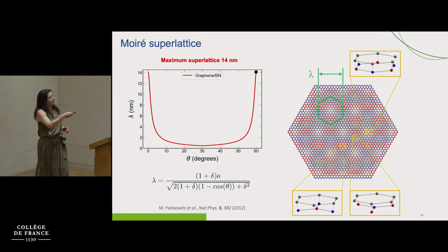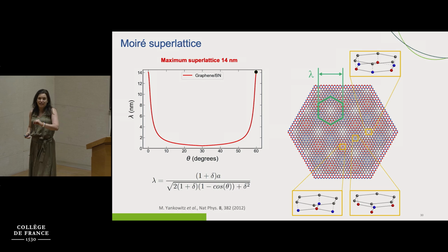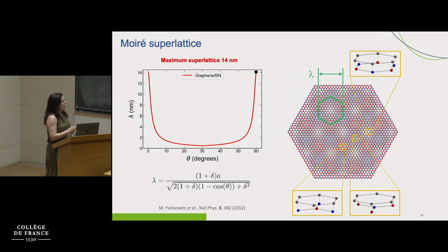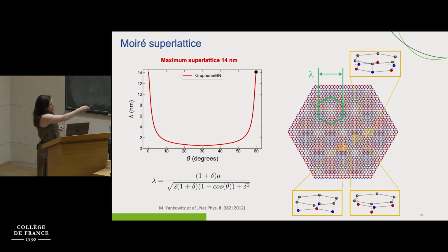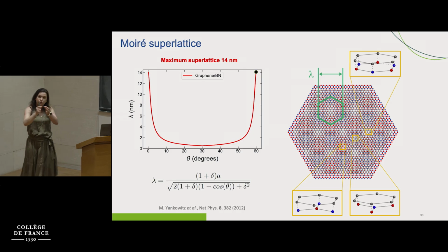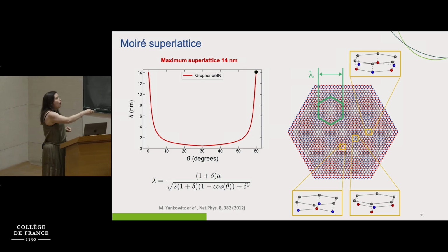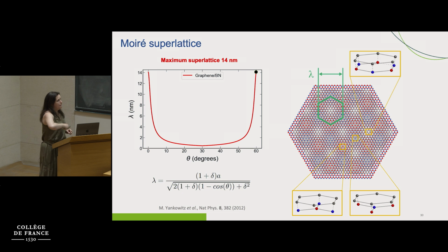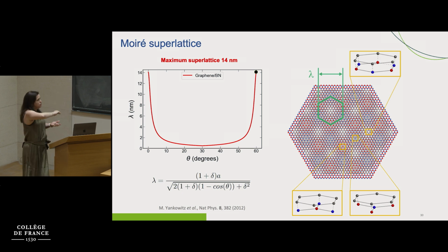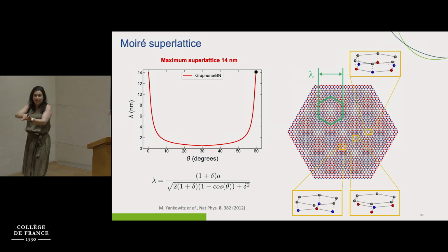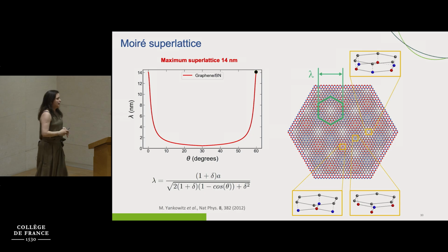In this case, I'm using the example of graphene on boron nitride, which has a difference in lattice constant of 1.8%. So the size of this new moiré lattice is going to depend on the difference between the two lattice constants and the angle between them, which means that just changing the angular alignment between the layers, as you saw in the animation, I'm going to be able to go from something very close to 0 as a moiré superlattice to something very large, around 14 nanometers.